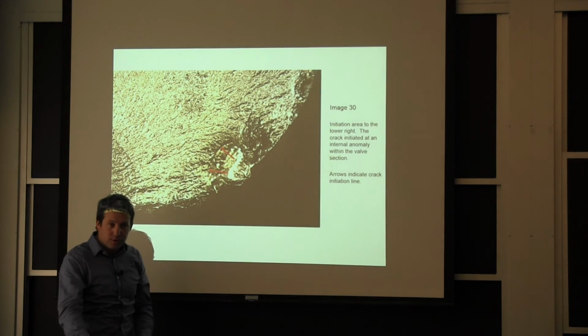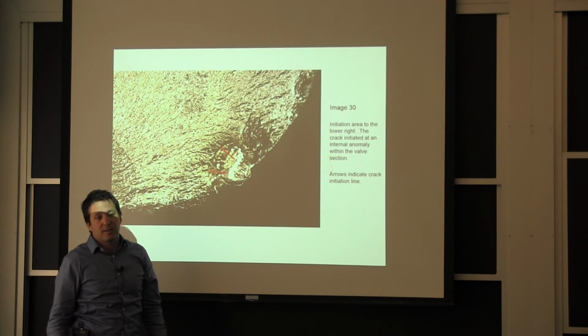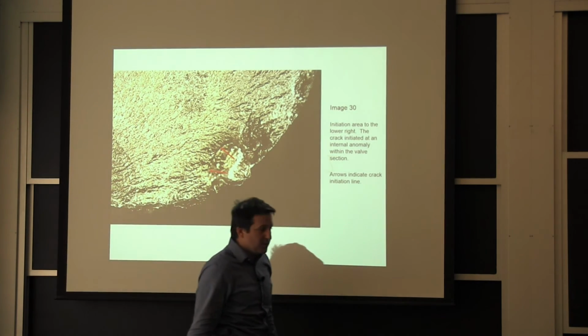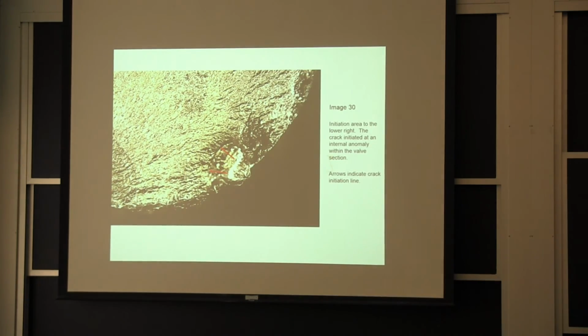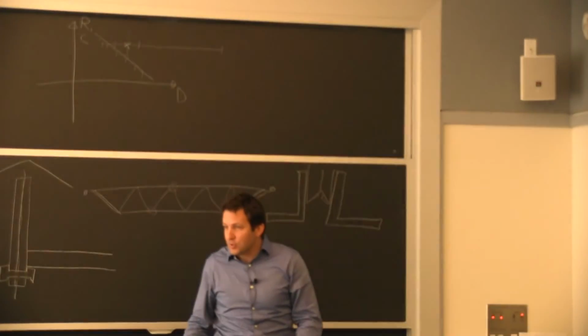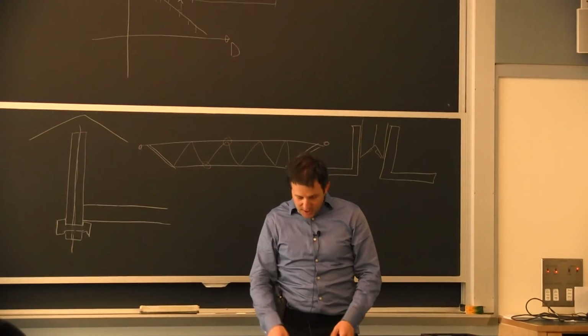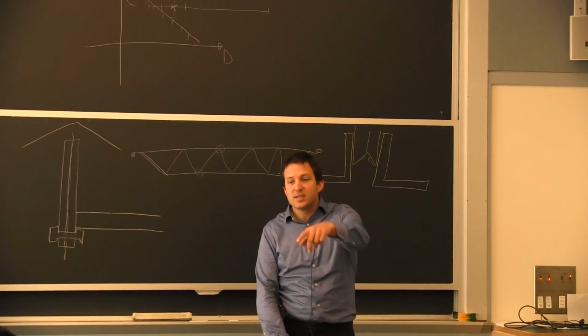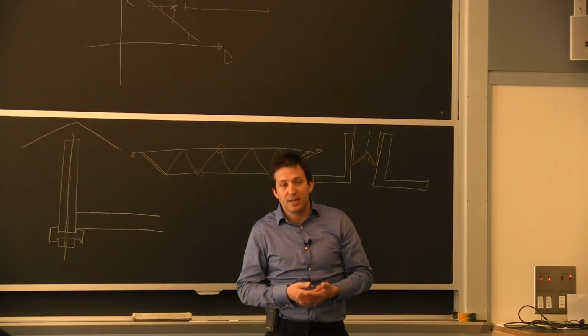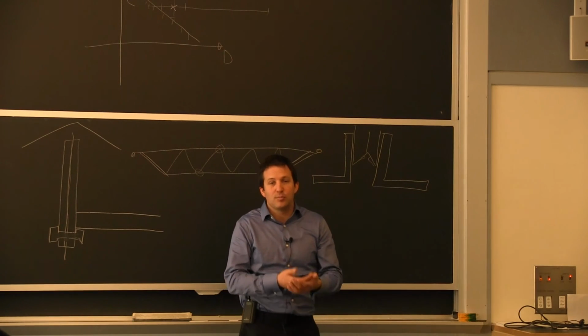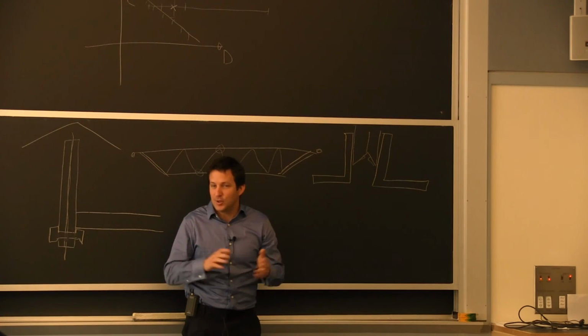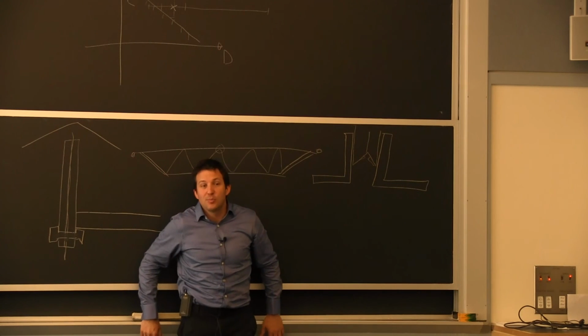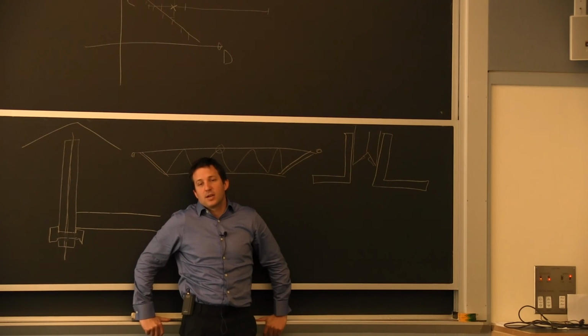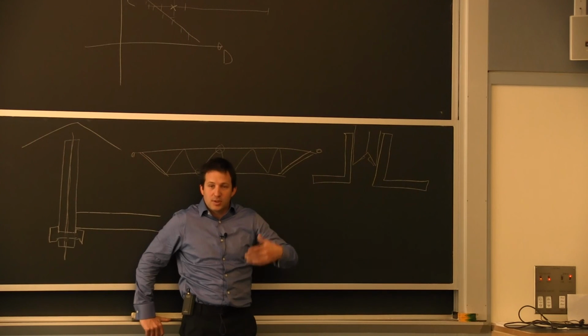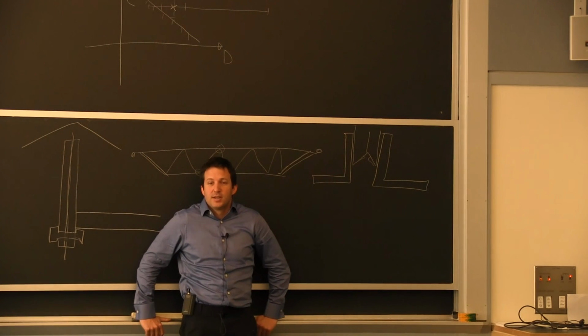I formed the corrosion pit, and then I started the crack, which means at some point the engine, which is 25 years old, my guess is for 5 years it hasn't been used, and it started corroding. I had all these pits, and you can see it on the side of the shaft. There's a lot of pitting. These pits happened before the crack initiation. Everything was fine up until I started pitting that shaft, and that caused the progressive damage, and then a couple of years later it failed. So that was the lesson learned from that one.